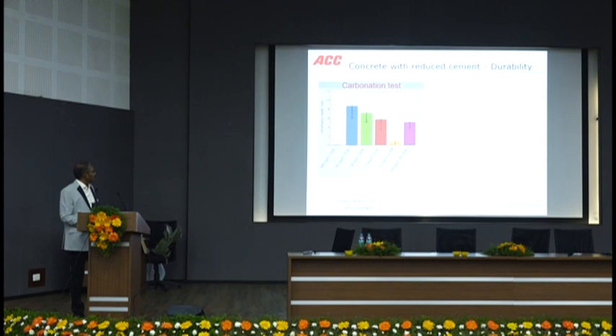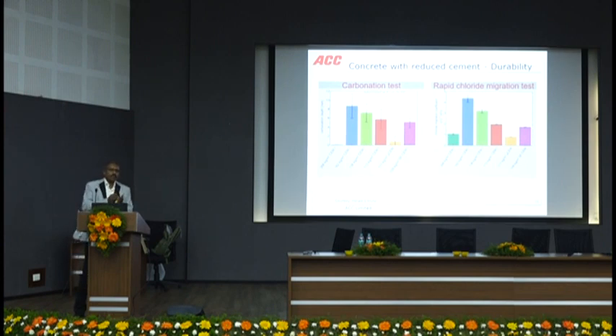And you see here, just try to correlate these studies. With the 260 cement content, the carbonation depth is just negligible, whereas the 160 kg cement content shows a higher carbonation depth, whereas the high fineness cement shows a carbonation level of around 1 mm. Why does the 160 kg show more than the 260? The cement is the same, but he used more water content. When you have more water content, then obviously a lot of porosity will be there. When the porosity level is more, the carbonation depth shows more.